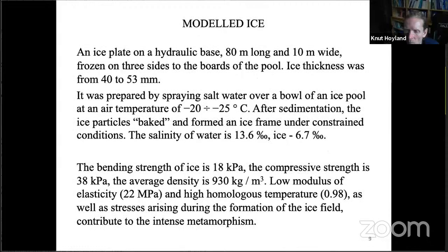At the Krylov Research Center location, the modeled ice was prepared in a special way. It was frozen on 3 sides to the borders of the pool by spraying salt water at low air temperature. As a result, the strength values mentioned on the slide were observed. It also includes low modulus of elasticity and high homologous temperature.